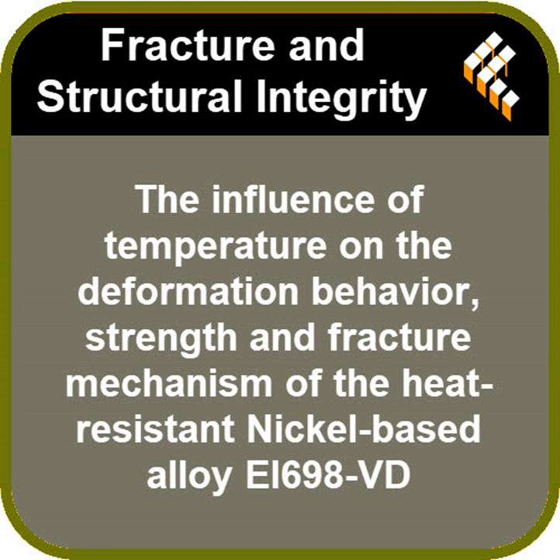To see the real cause of death, they had to look at the fracture itself. So they put the broken pieces under a scanning electron microscope. And this is where the picture becomes crystal clear. At lower temperatures, the breaks were transgranular. Meaning the crack just tore straight through the individual metal grains, a typical high-energy fracture.